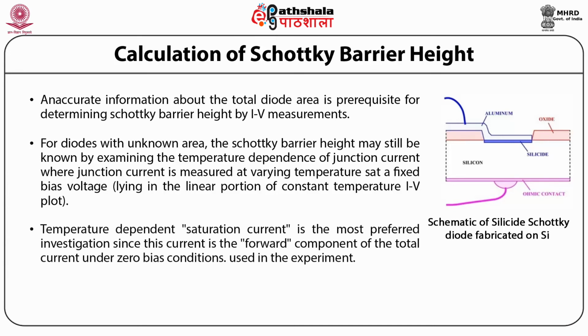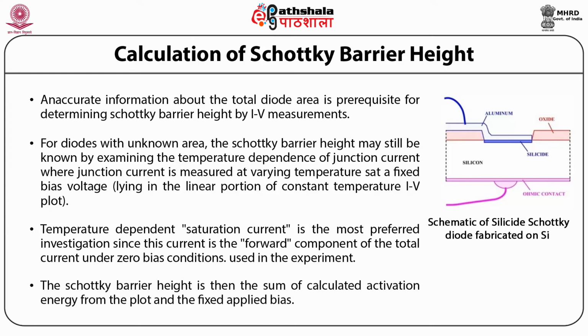A temperature dependent saturation current is the most preferred investigation since this current is the forward component of the total current under zero bias condition. The logarithm of I divided by T squared, that is I times T to the power minus 2, can be plotted in the Richardson plot as a function of inverse temperature, T to the power minus 1. The Schottky barrier height is then the sum of the activation energy calculated from the plot and the fixed applied bias used in the experiment.